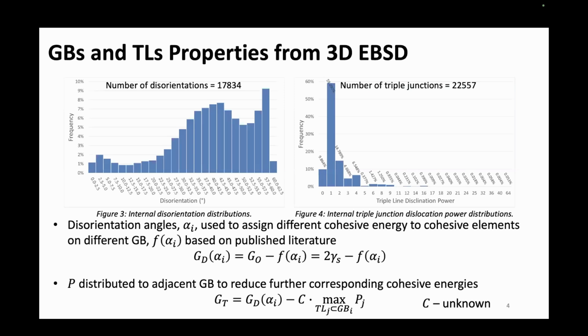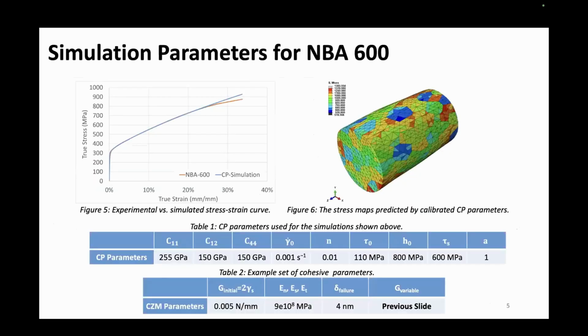And then that's our novel approach: integrating the effect of the triple line junction into the GD model further, to account for the effect of triple junction disclinations. With all three models, we are trying to account for the grain boundary excess energy more accurately, to better simulate the intergranular cracking. Our aim is to capture the behavior of alloy 600.